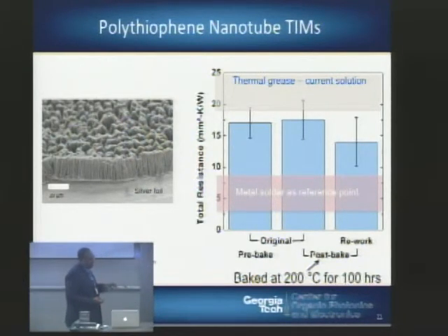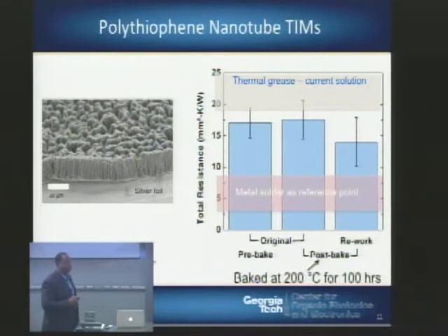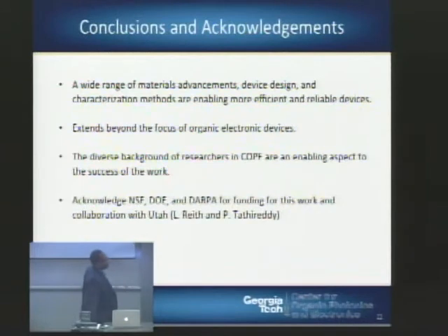In addition to this, you also have very nice compliance by using these polymer nanotubes. That allows you to put materials together with different coefficients of thermal expansion without transferring a lot of stress to the die, which can actually be detrimental to the performance of the die. So with that, I'm a little bit behind the scheduled lunch, but trying to catch us up.